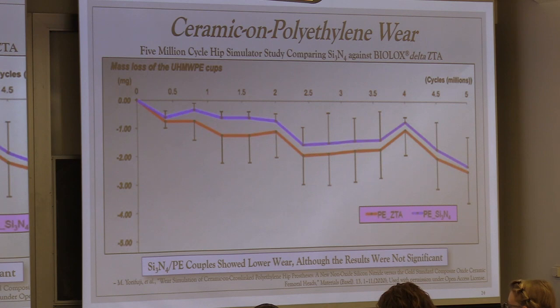So silicon nitride actually, in this case, for this 5 million cycle test, outperformed ZTA at every time point that was examined, although you can see by the error bars that it wasn't statistically significant, but it did show that it was basically equivalent to the predicate. So my case here would suggest that silicon nitride should be a good material, very comparable to the standard that exists out there already. But that's not the whole story.